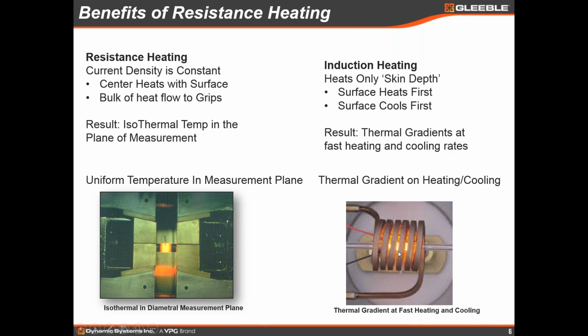But if I'm trying to do a welding experiment or something that has a very high heating rate, like laser cutting or torch cutting, I am not going to be able to heat at those kinds of rates in an induction heating or in a furnace system and keep a good thermal gradient through the sample. So what that means is the surface is going to heat first, the center is going to be cold, and I'm going to get a little bit of a distortion in my dilatometric curves. The curves are going to broaden and they're going to shift because I'm not really measuring the temperature through the whole sample. I'm just looking at the surface temperature. The center is colder, so I'm not going to get a real good result from that.